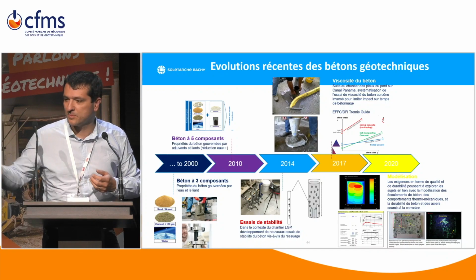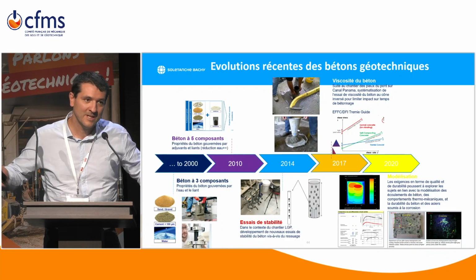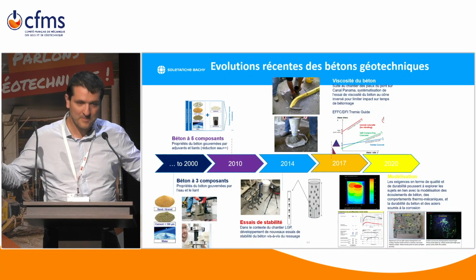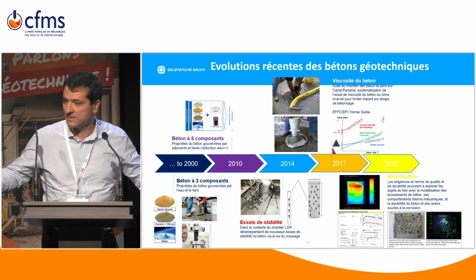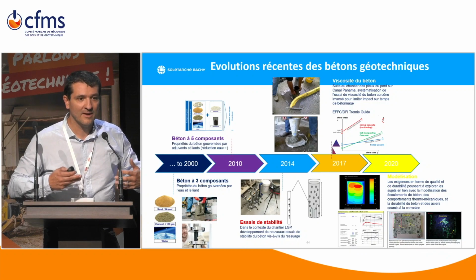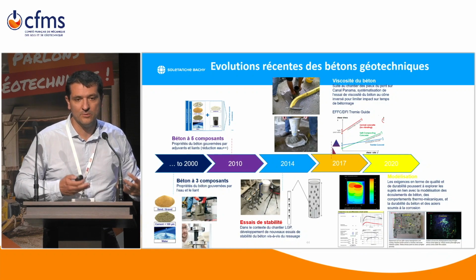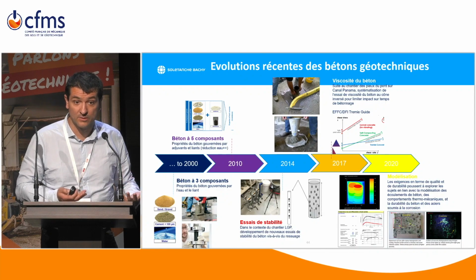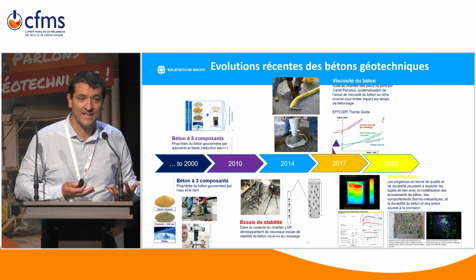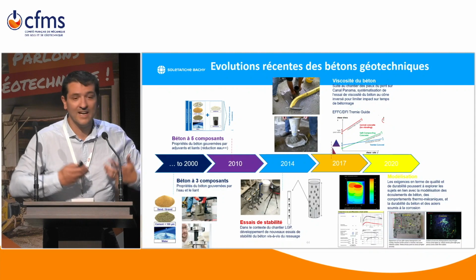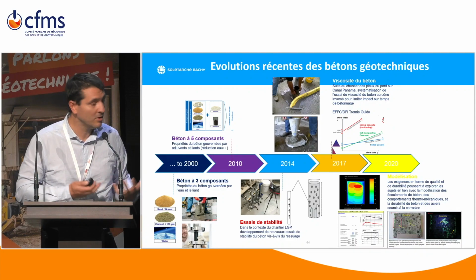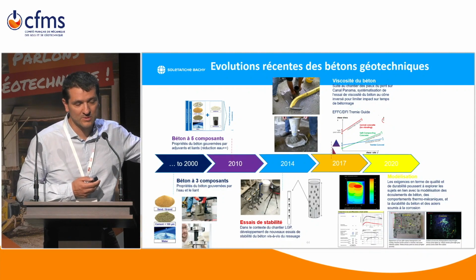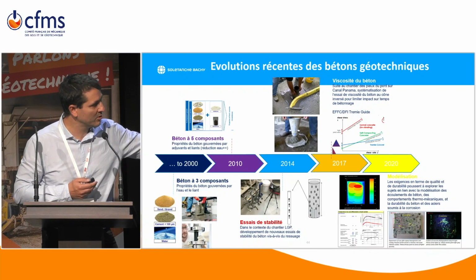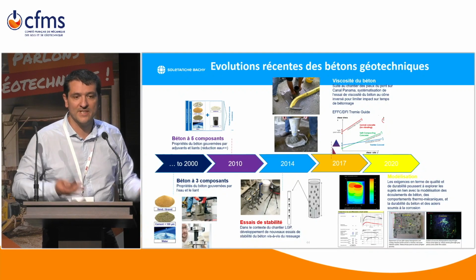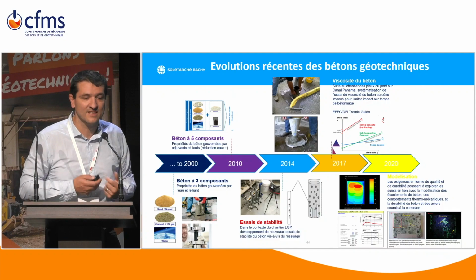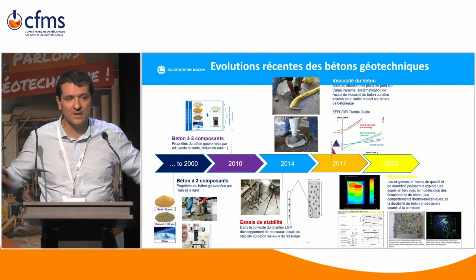Another issue: we are speaking about 2.4 meter D-walls, for example, in Japan. So that means that with geotechnical concrete, we are facing the same issue as mass concrete. The heat of hydration of the cement can build high temperature within the core. And there was also a need to develop modeling and numerical tools to predict and also to control on site the temperature in the very large pour.